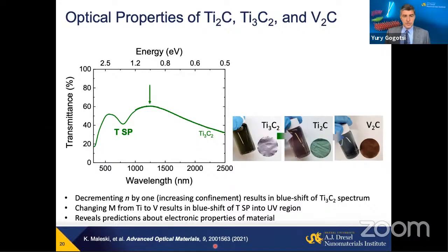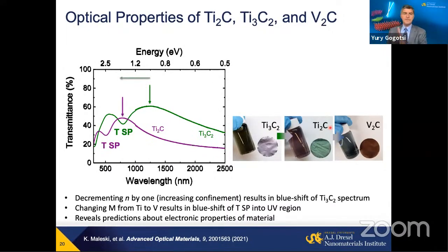And if you change the transition metal, or basically the thickness of the layer, from titanium 3C2 to titanium 2C, make it thinner, you shift it. The surface plasmon of titanium 2C will be at about 550 nanometers. So you change the color in transmission from green to red or reddish, but in reflection, those will be complementing colors. So titanium 2C actually will be green and titanium 3C2 will be kind of violet here.